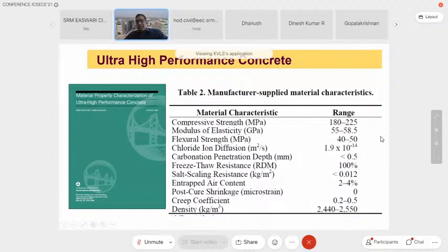We're talking about compressive strength basically on an average around 200 megapascals. So it's extremely strong concrete with a very high modulus of elasticity. But more importantly, if you look at the chloride ion diffusion or the carbonation resistance, the freeze-thaw resistance, the creep and shrinkage, these are all extremely superior compared to normal concrete. So this is a concrete that delivers on a performance at a very high scale. But of course, this very high scale performance comes at a cost, because you cannot deliver this level of performance without improving not just your material mixture, but also processing, because ultra high performance concrete requires high level of processing, and that adds to the cost of the material.